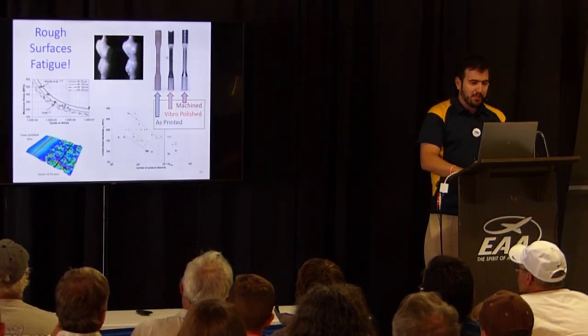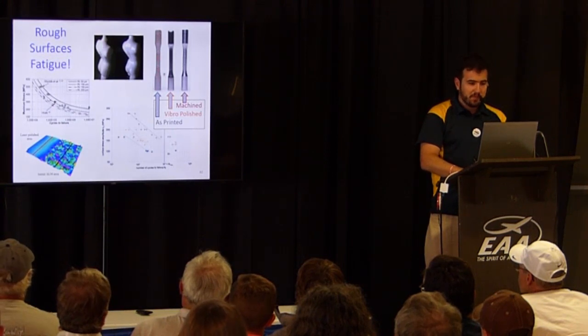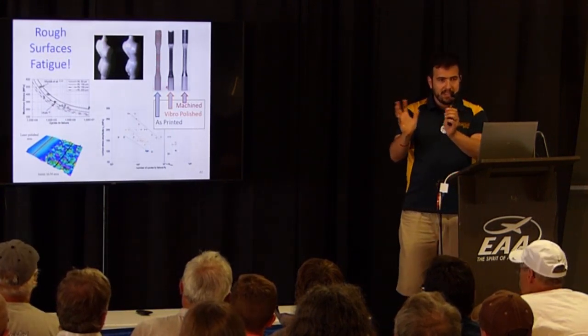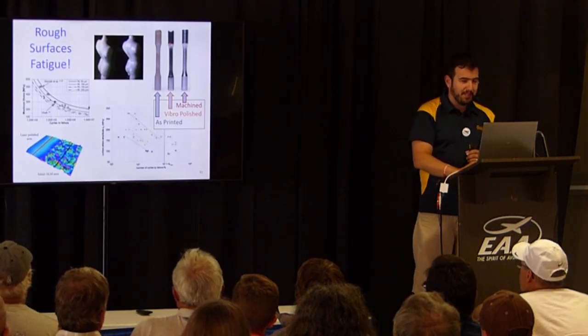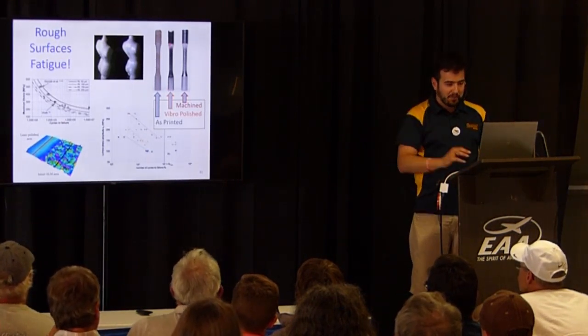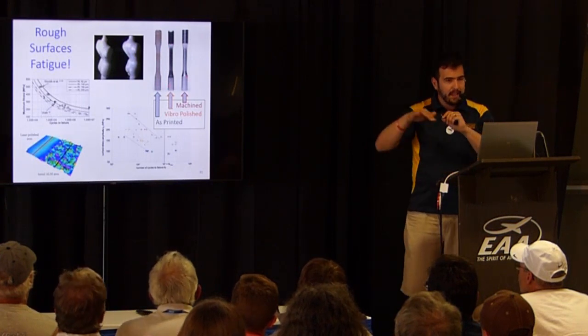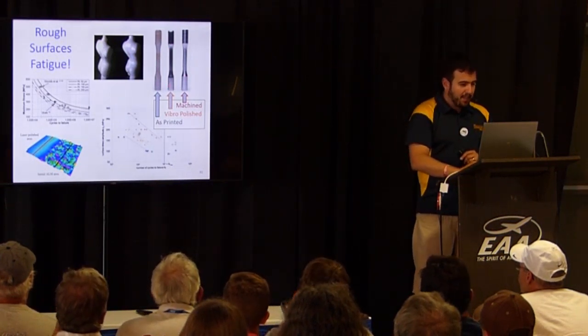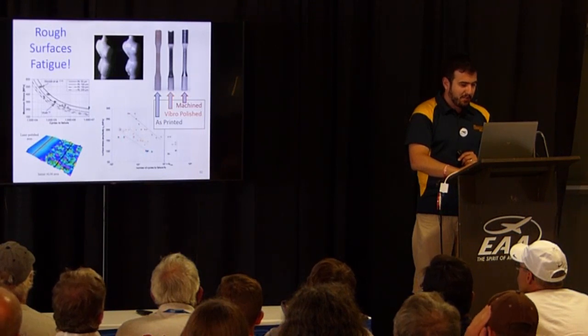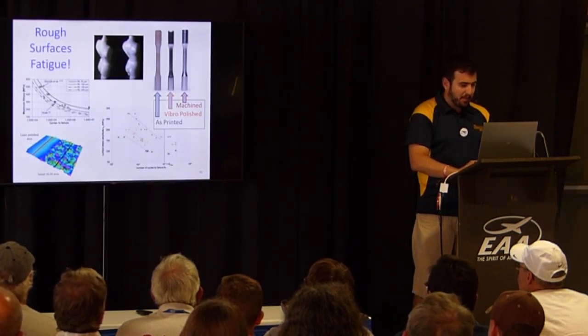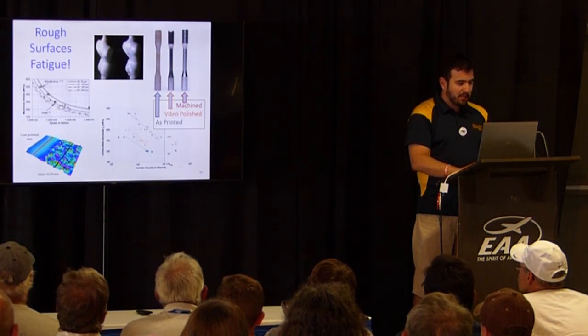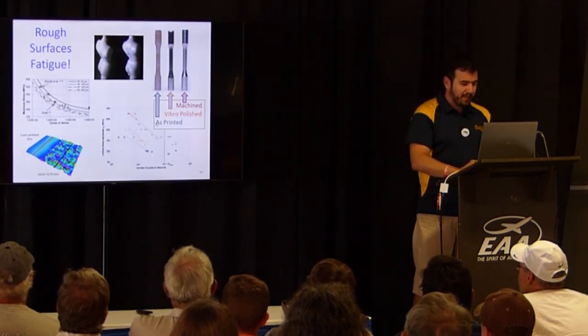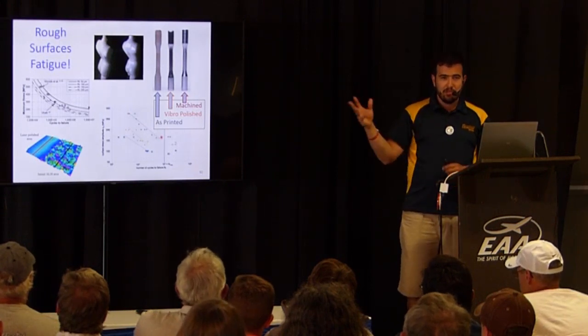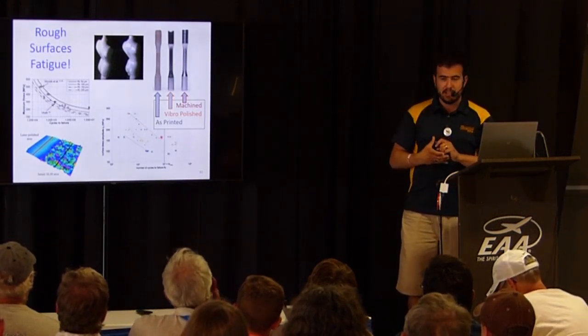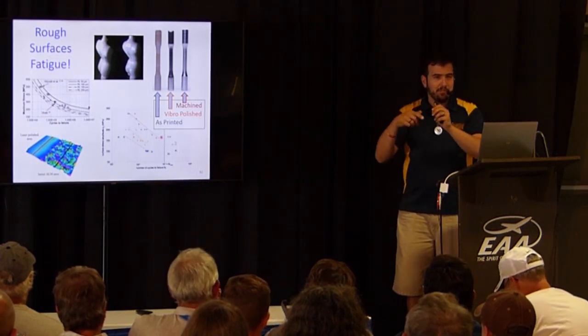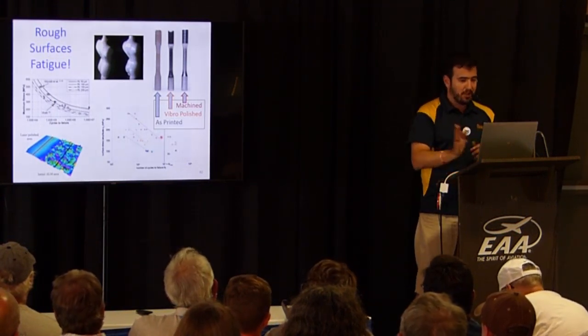So for example, here's a 3D printed little dog bone test specimen for fatigue. If you put it in a vibrating tumbler with sand, it automatically smooths the surface without you having to do a lot of work, you get this. And if you do put it in a lathe and smooth it out, you get that. And here are the fatigue lives. The as-printed one is down here. The automatically vibro-polished surface is right here. And the machined one, the one where we actually do it by hand, is up here. So doing these automatic chemical bath, vibrating tumbler things isn't as good as machining the surface by hand, but it gives you something. So there's a lot of research on this.